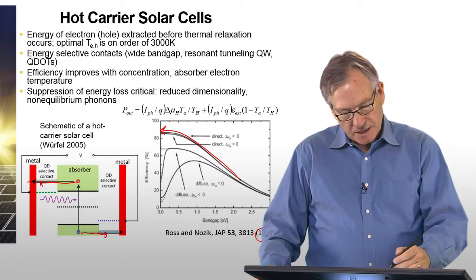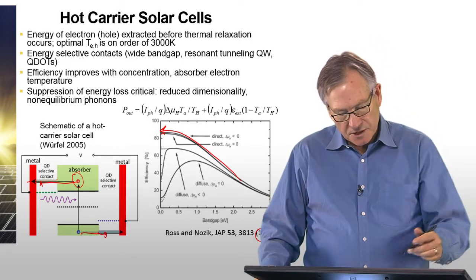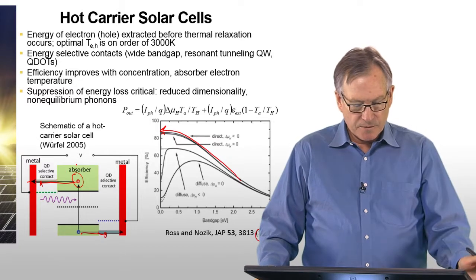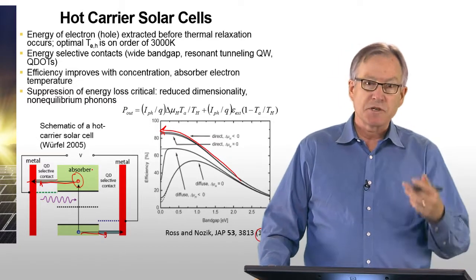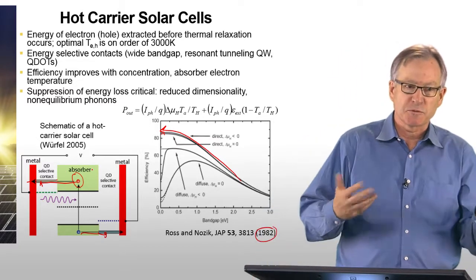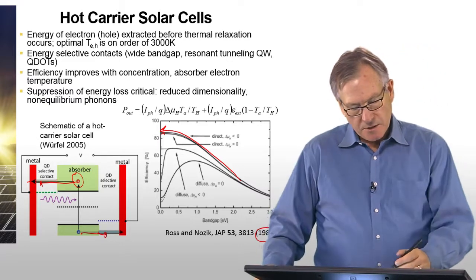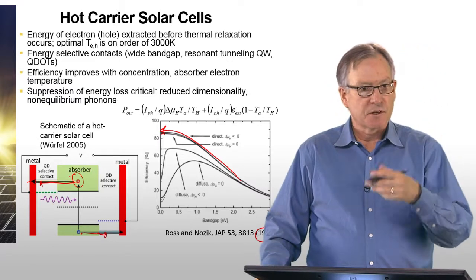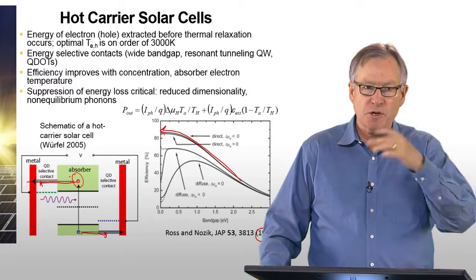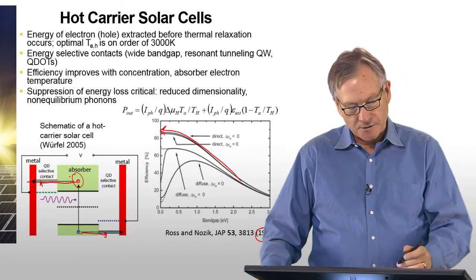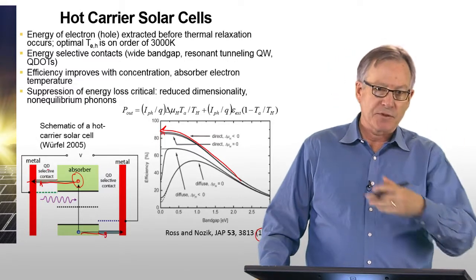The problem is that the ability to capture or keep the energy of the electrons in this absorber is extremely difficult. In bulk materials, it's practically impossible because the rate of phonon emission occurs at a sub-picosecond time scale. So there isn't even time to get out of the contacts.